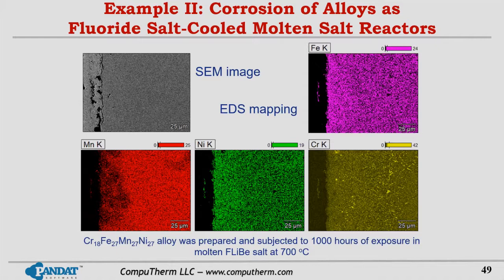So in this SEM image, you can tell this reaction layer, and also from this EDS mapping, you can see this diffusion affected layer. For example, if you focus on this red mapping, that's the manganese. So as you can see, in the diffusion layer, manganese is depleted.